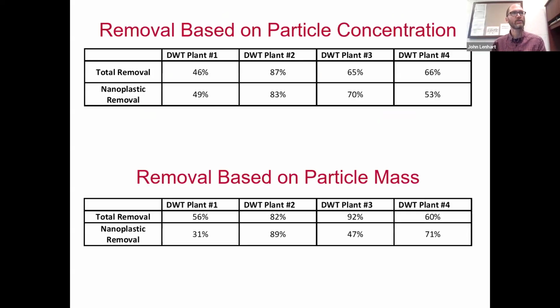So to summarize all these results here, you can see for the 4 plants we've depicted the total removal and then the nanoplastic removal. Top is based on the particle concentration. Bottom is based upon the particle mass. We see removal overall anywhere from 50 or so to 90% based on particle concentration, and similar percent removals based upon particle mass. The removal based on particle concentration is maybe a little bit more consistent than it is in particle mass, where we see a little bit more variation.